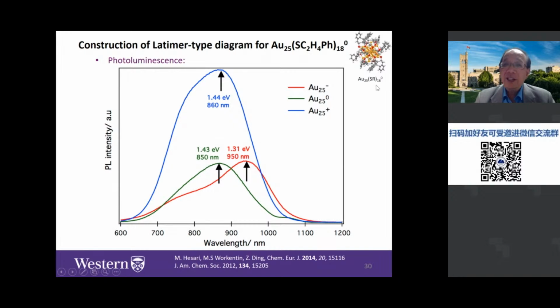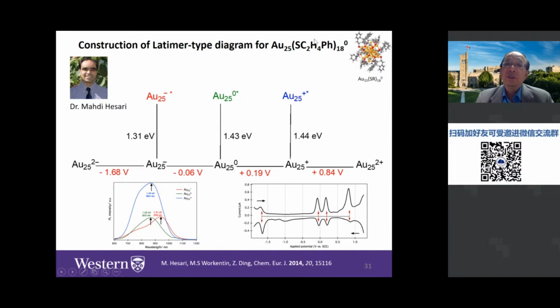So now we took these three values and put them together. Gold 25 negative can be excited to the gold 25 negative excited state, it's 1.31 eV. And similarly, gold 25 zero to its excited state, gold 25 plus to its excited state. And as I said, this was done by Dr. Mahdi Hesari, who was a PhD student in my group and in my colleague Dr. Workentin's group. He's a joint PhD student. In Workentin's group, he was making the compound, and in my group, he was measuring the electrochemistry and photoluminescence.